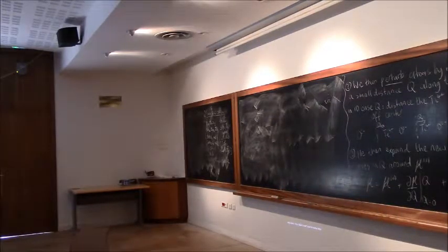Okay, so let's have a look at this first term. This is the first order correction in perturbation theory. The Hamiltonian of a system is totally symmetric, and Q, the distortion that we're making here, is a polar distortion. It has odd symmetry. My zeroth order wave functions are also totally symmetric. So here I'm making an integral over a product of two even things and an odd thing. So what happens if I integrate over all space a function that's overall odd, that has odd symmetry? It goes to 0. So for the case of Q odd, provided I don't have subtleties like degeneracies, this term goes to 0. So for ferroelectric distortions, I don't have to consider this further.